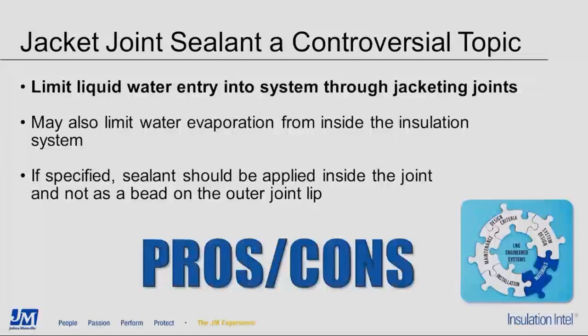One thing we're asked about fairly often is jacket joint sealant, and this is caulking to eliminate water entry through the jacketing joints, circumferential and longitudinal. We don't have any test data or science on this, but it does seem to make sense. One caution, though, is it may also limit water evaporation from the inside of the insulation system out. But in the LNG applications, it might be a sensible thing to do. Again, we just don't have any data on it. But if it is specified, the sealant should be applied on the inside joints of the jacket, longitudinal and circumferential joints, and not as a bead on the outer joint lip.